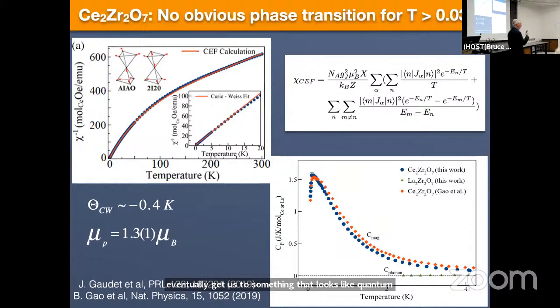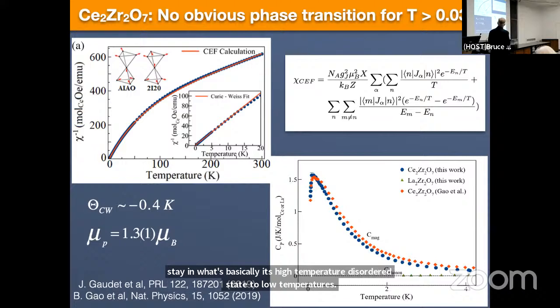So one of the main features that we're looking for initially in candidates for quantum spin ice is evidence of no phase transition as you lower the temperature. So we don't want the system to order, we don't want it to freeze, we don't want it to do anything, right? We want it to sort of stay in what's basically its high temperature disordered state to low temperatures. So we eventually made cerium zirconate in single crystal form. And this is some of our initial characterization.